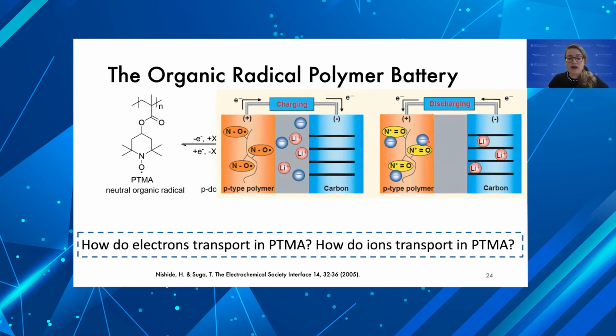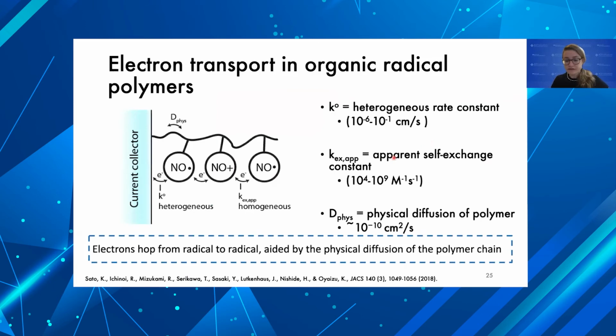So in that idea, we want to know, how do the electrons and ions transport in this cathode? In a collaboration led by Hiro Nishide and Kenichi Oyaizu of Waseda University, we learned that electrons are hopping from radical to radical, aided by the physical diffusion of the polymer chain. The way this works is that you have electrons hopping between sites in the chain or across chains. We consider that to be a homogeneous electron exchange. And finally, as a last step or a first step, the electron can hop into the current collector.